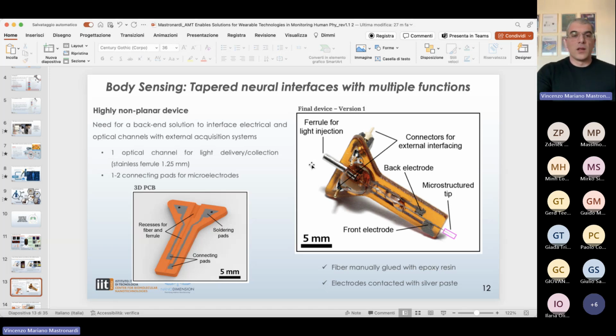This is the first release, the first generation, of this electrical interface, and it has two main problems. One is related to the manual gluing of the fiber into the recesses using epoxy resin, which reduces the robustness of the gluing and of the fiber itself. The second problem is related to the connection between the connecting pads and the electrodes placed on the fiber, which we initially fixed using a conductive paste.